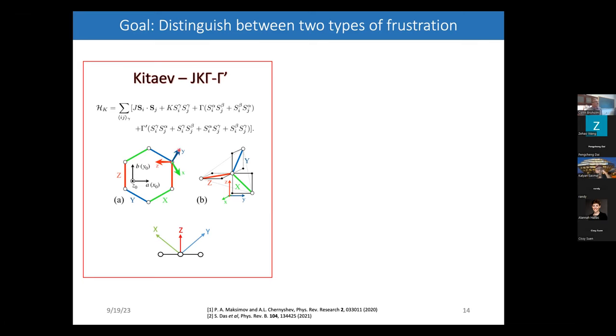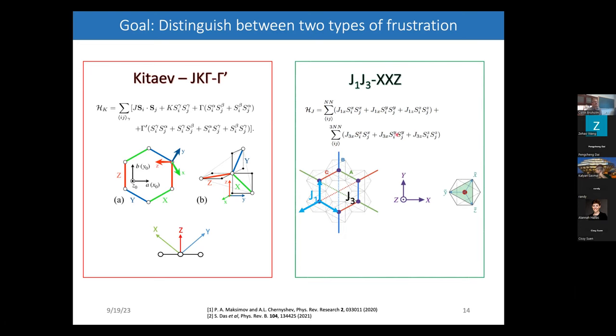Thank you. The projections onto the honeycomb layer are perpendicular to the nearest neighbor bonds, but the XYZ axes come out of the plane in such a way that the 1,1,1 direction is oriented directly along the C axis of the system. The geometry is easy to get lost in, so we're actually dealing with two different coordinate systems in this talk. To describe the Kitaev interaction, we use this XYZ coordinate system, with all axes sticking out of the plane, oriented like that. To describe the XXZ interaction, we use a coordinate system which has X and Y directions in the honeycomb layer, and Z coming out along the C axis. That's perhaps the more natural frame to be thinking about.